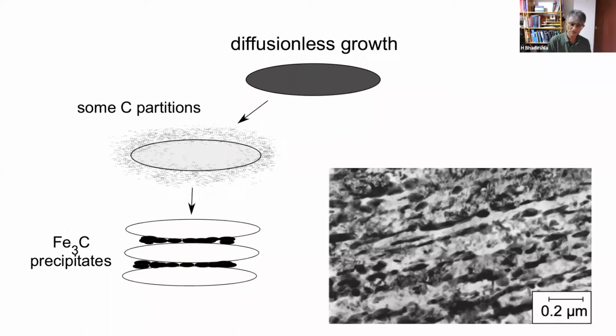Okay, so the fact has been known for a long time, but we wanted to calculate how much silicon we should add, because it also has other consequences. Now, the reason why silicon stops the formation of cementite at low temperatures is because the cementite is then forced to absorb the silicon, and it absolutely hates the silicon.